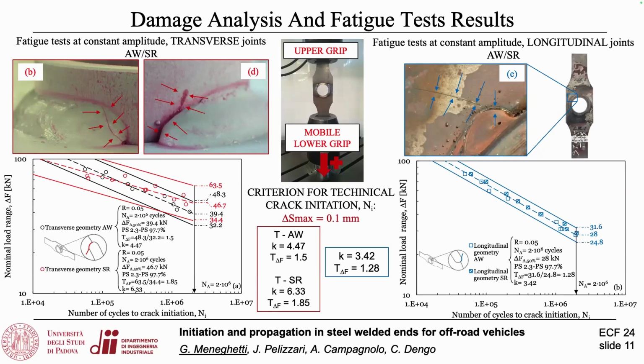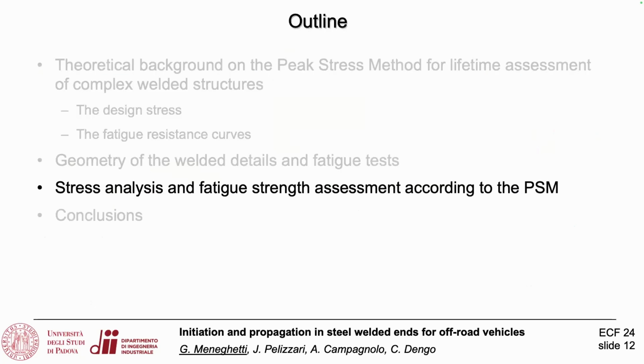If we look at the transverse joints, things are a little bit different. We see some effect of the stress relieving, but I want to bring your attention to another point. Look at the slope. We have a more gentle, more flat slope of 4.5 or 6.3. So flatter than we observed in the longitudinal joints. And people familiar with the fatigue of welded joints, as soon as they see flatter slopes, think that the crack propagation phase is particularly long, and this is the explanation in this case, as I will show later on.